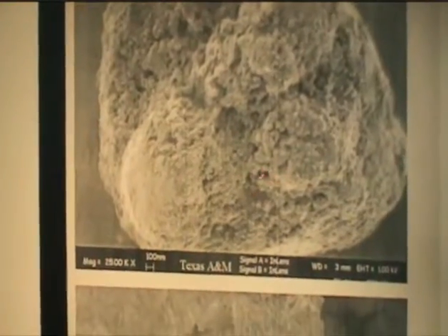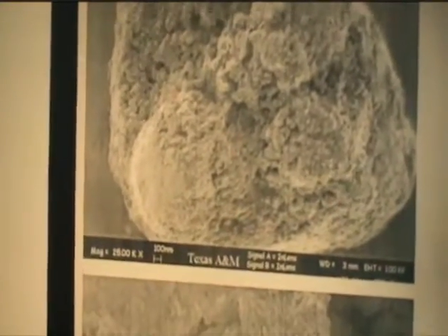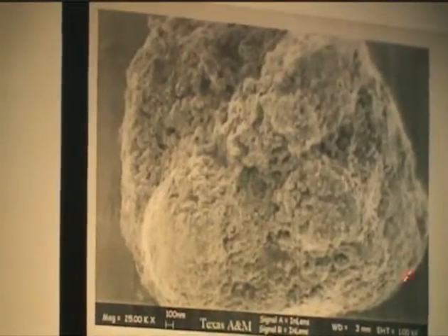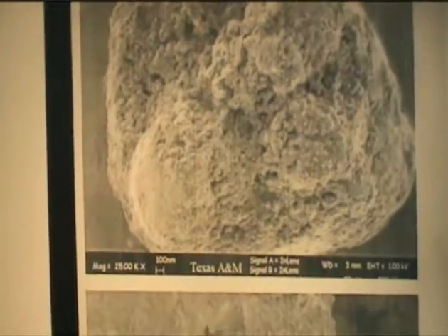This is also 100 nanometers, but notice that the bar is much smaller than it is here, so this is much bigger. And it looks like some of the spheres have fused together, and that we now have some fairly big openings here. So there is something happening to those little spheres during the reaction, that they come out in a different topology than when we started.